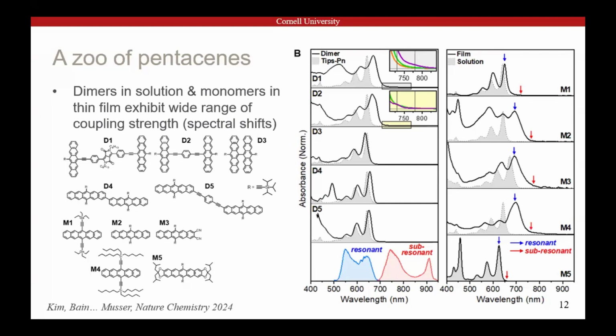And we decided to try the most ridiculous simple experiment we could to see, well, does the triplet pair state absorb? We tried to excite it. So on the surface, this looks like a silly experiment to do. We're going to compare transient absorption spectroscopy, either pumping resonantly with this blue pulse or these blue arrows, versus subresonantly, something below the band gap where it doesn't really absorb, but where we think the triplet pair state might be. And the reason we thought this could possibly have a chance to work is because in a couple of our dimers, we saw very weak structure below the band gap that roughly lines up with where the triplet pair state should be. So we thought maybe there is a state down there, just very weakly absorbing.